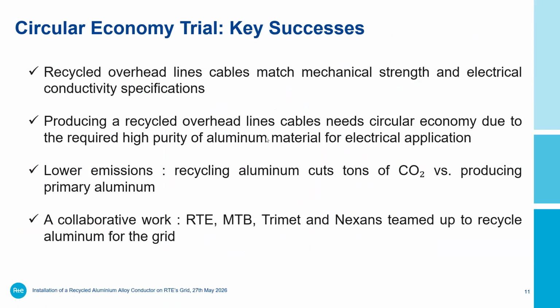Concerning this trial, the first conclusion is we managed to produce a new cable securing the mechanical strength and electrical conductivity. Also, we noticed that if we want a new cable with recycled content, we need circular economy, because we have to be sure about the quality of the aluminium we inject for electrical application. This practice also permits lowering the emissions. Recycled aluminium cuts tons of CO2 versus primary aluminium.